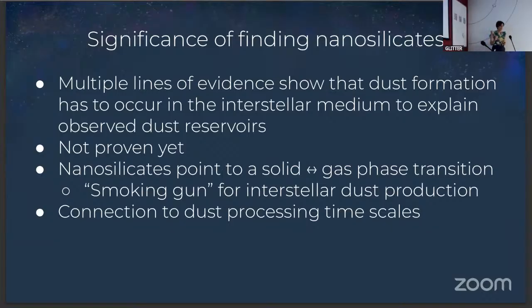So to detect nanosilicates, that really points to the transition between solid and gas phase, between the constituents that silicates are made of and the bulk material silicates. Nanosilicates fill that gap in between. So it's kind of a smoking gun for interstellar dust production, or dust destruction, of course. It is in between. It actually points to this transition between these two components. But having a population of 10% of these grains is really significant, and we can now try to include that into the models that we have that explain dust processing.